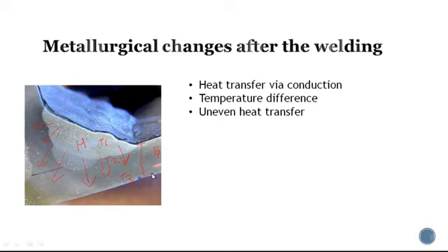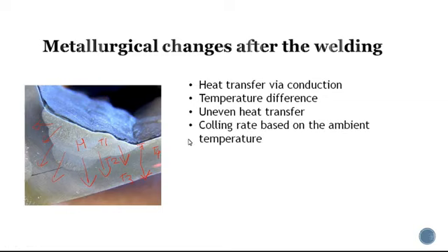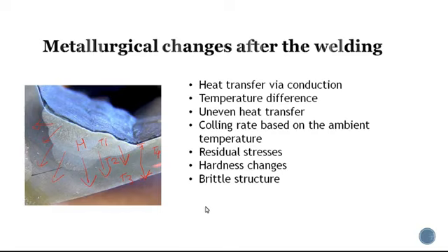Sometimes uneven heat transfer is also because of thickness. The heat transfers differently to the thick area and the thin area, so the temperature distribution is different. Once it starts cooling, it depends on the ambient temperature, and the cooling rate also changes based on the circumstances. Because of all this, residual stresses and internal stresses are generated, and because of the residual stresses and cooling rate, the hardness value changes, and that makes a brittle structure.